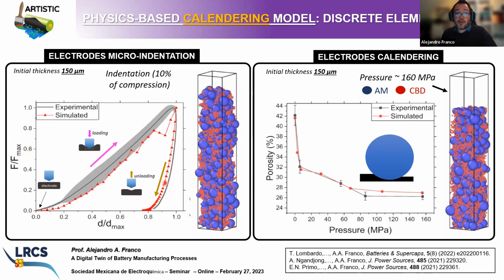And then you can simulate this by using this method, and by comparing results from the model with the experiment, you can calibrate the parameters that you need to put in the interaction forces describing the interaction between these particles upon calendaring. And also we have calibrated these parameters simultaneously to compaction curves. In a compaction curve, we represent the influence of the calendaring pressure on the electrode porosity. Okay, and you see here also a very good fitting with the experimental compaction curve.